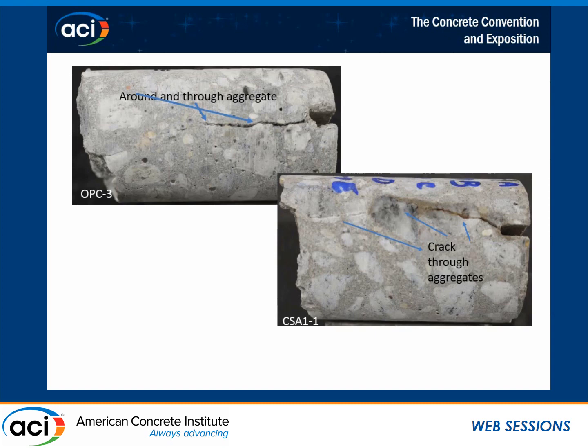This is some samples now coming off for the next part of the study. We got a little more sophisticated moving in later on, so we started taking pictures of our cores and looking at them. You can see here a typical one: here's our notch, here's the crack coming down, and then we stopped. The core came from the back side to get to where the bottom bars were, so we didn't want to go into the back bar. So you can see the crack arrested.